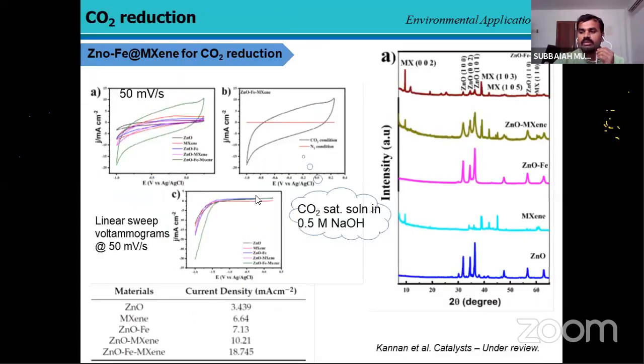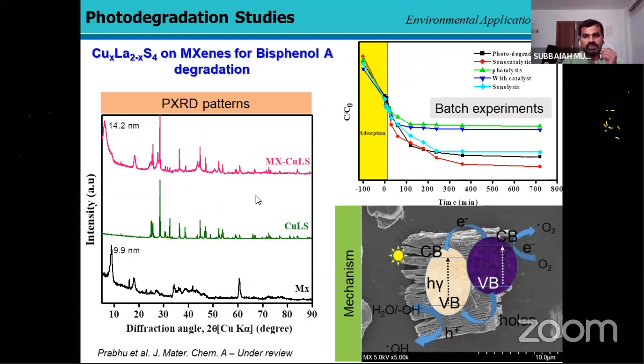Another similar work was done here in Alagappa University. We have started copper lanthanum sulfide and MXene for bisphenol A degradation. We found that these particular bimetal oxides are intercalated, confirmed by PXRD studies, when the d-spacing value increased drastically from 9.9 to 14.2. This MXene material was totally delaminated.